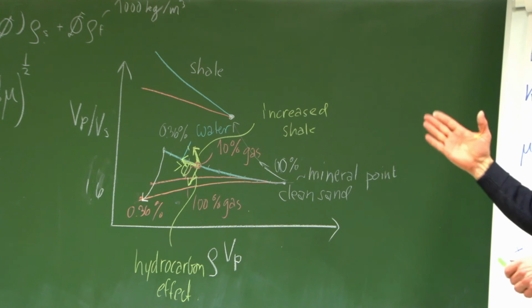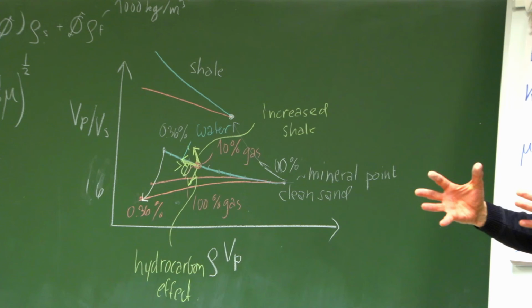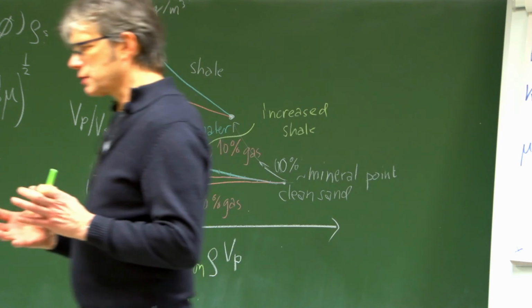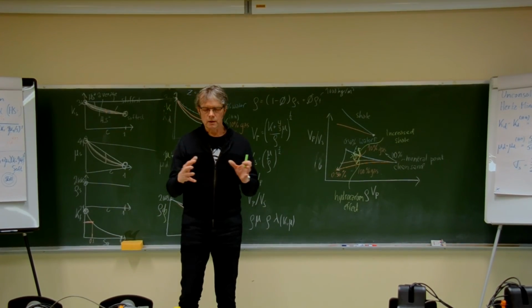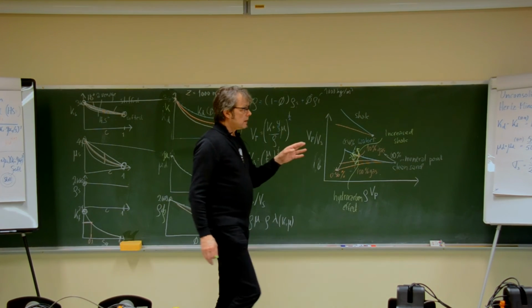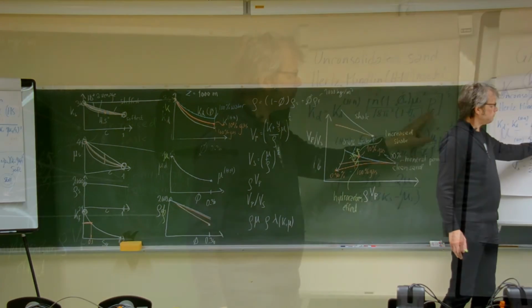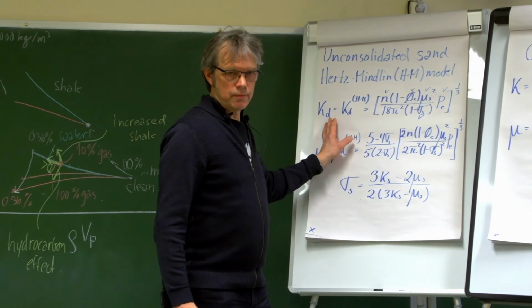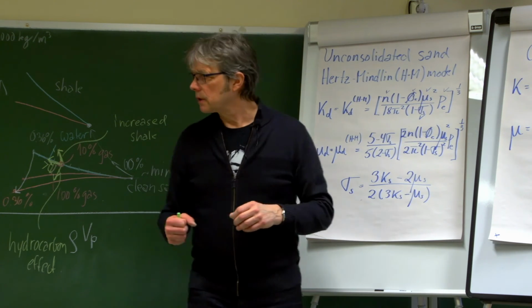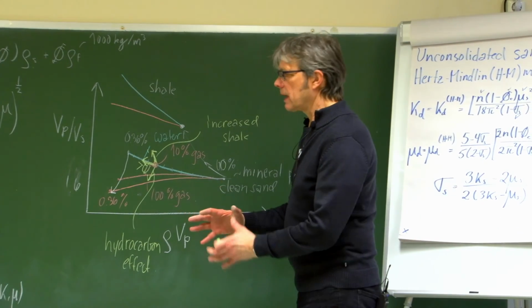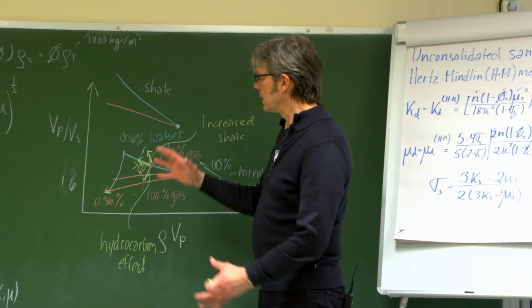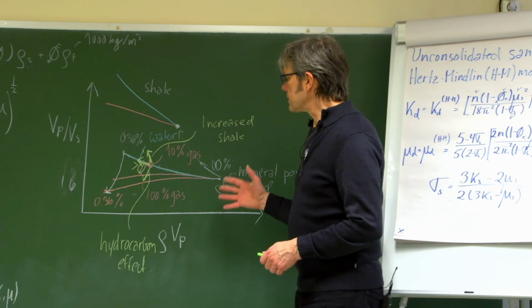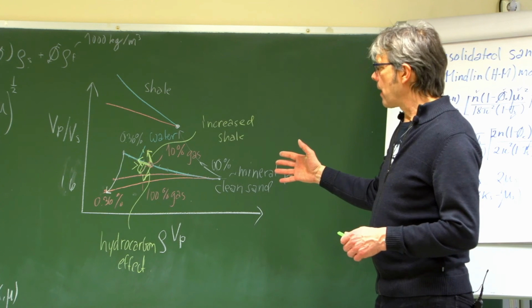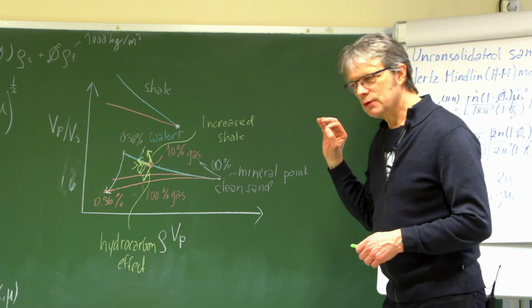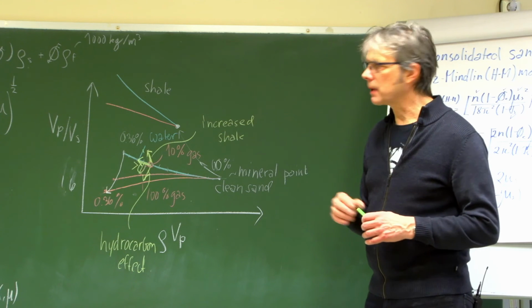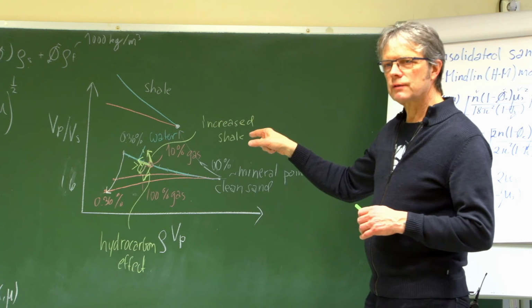And then I could also have shown you what happens when, for instance, I'm increasing the pore pressure. Let's say I had an anomalous pore pressure, not given by this simple equation, but I was increasing it. What would happen then? Yes, with the dry rock properties, it would make the system looser. So the elastic properties would be reduced. So in fact, the effect of increased pore pressure would also move in that direction because it's looser. Okay, so this is how you make a template. It's bits and pieces that need to be put together, but this gives you the roadmap. So in a minute, I'm going to show you what happens if it starts to consolidate.